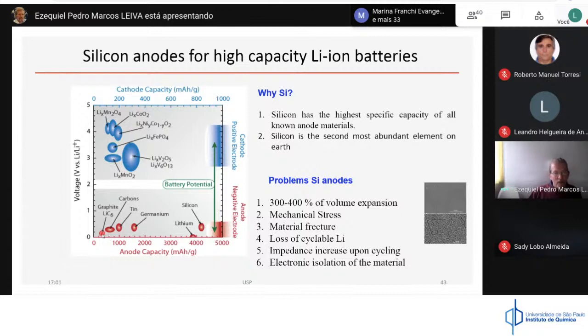Graphite is the material that you have in your handies now. This is the typical anode material of commercial batteries, but you can see silicon is very promising. Why? Silicon has the highest capacity of all known anode materials, and silicon is also abundant. There is a lot of silicon on Earth. It is the second most abundant element on Earth. But silicon has problems. One of them is that when you lithiate silicon, its volume increases 300 to 400%, and when you take lithium away, you get these cracks.